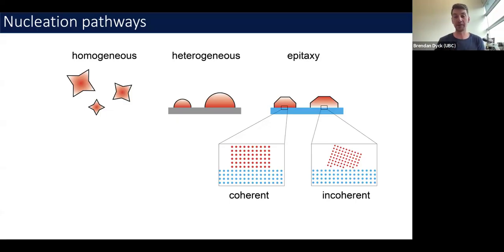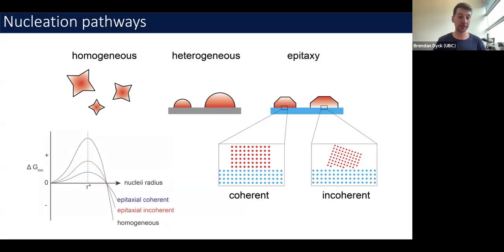Whereas incoherent grain boundaries might still impart an orientation relationship, or the daughter phase might still inherit an orientation from the parental substrate, but there is less of an atom by atom alignment or lattice alignment between those phases. And when we think about it from an energy perspective, the highest energy pathway here would be homogeneous. So there's this positive energy that is needed to overcome the initial surface energy of creating a new nuclei, right?